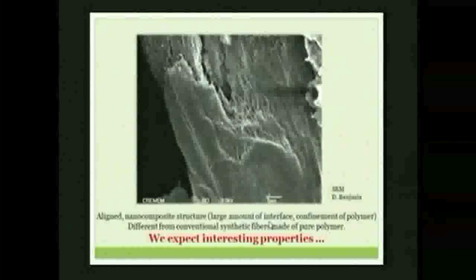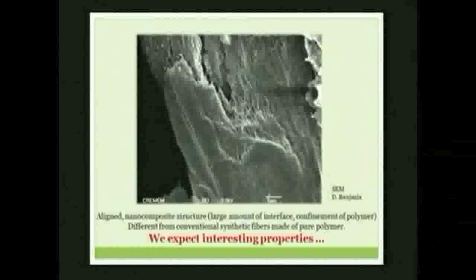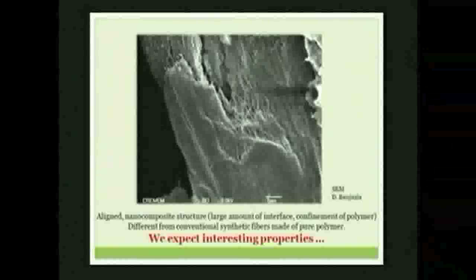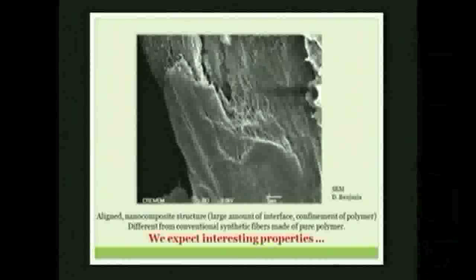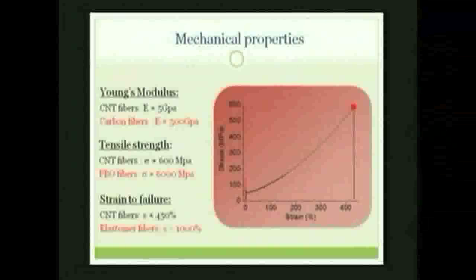So if you look inside these fibers, what do you see? You see these carbon nanotubes that you can guess here, okay? And they are not so badly aligned, okay? When you measure the alignment, it's not so good. But here it is not so bad. And these carbon nanotubes are embedded in the polymer matrix that you see all around. So it's an aligned nanocomposite structure with a large amount of interface. The polymer is confined in between the nanotubes. And we expect so the properties of this fiber to be different from conventional polymer because of the presence of carbon nanotubes. What are the mechanical properties?